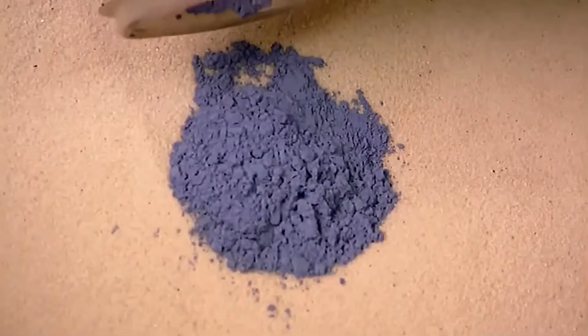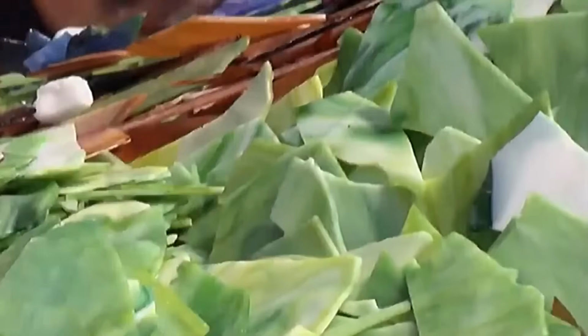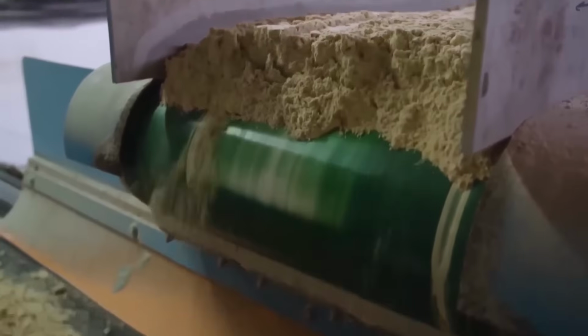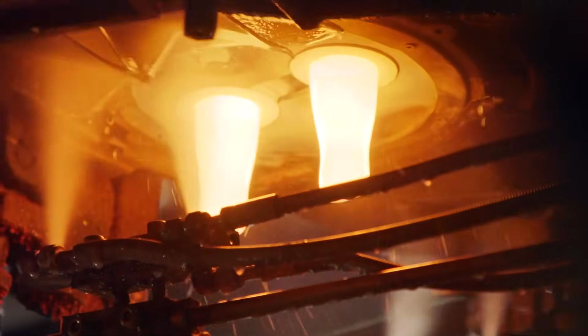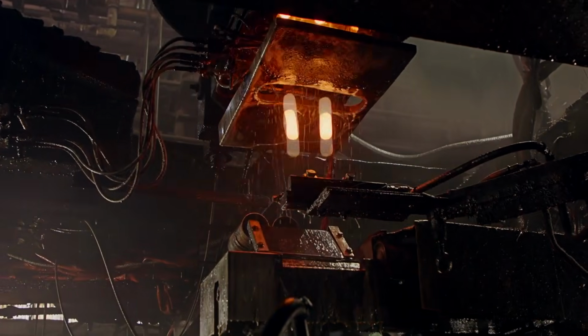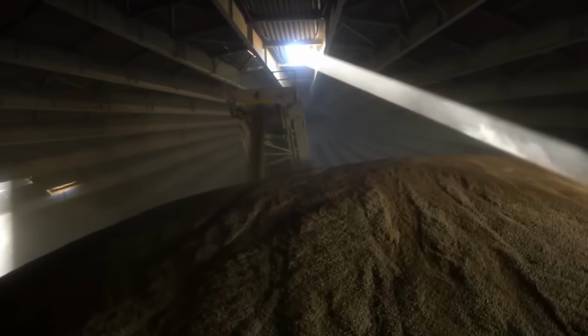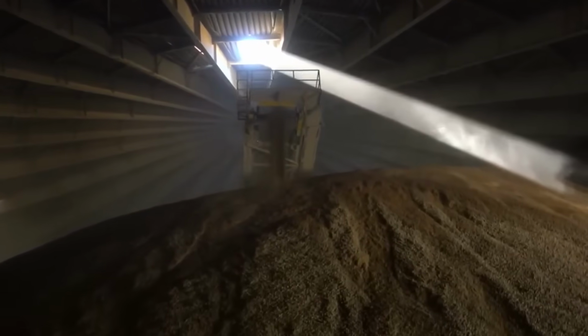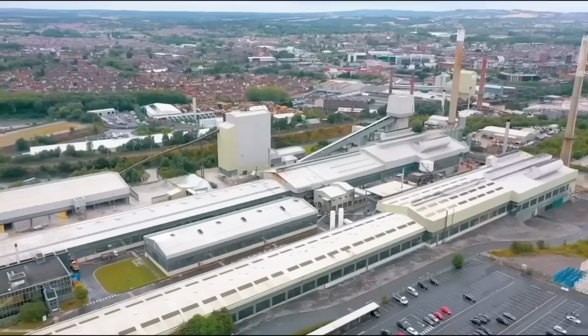The wash cycle runs for several hours per batch, and the overflow water carries the unwanted fines away through a series of settling ponds. After washing, the sand moves into industrial rotary dryers. These are large cylindrical drums, typically 15 to 25 meters long, rotating continuously, while hot air at around 300 degrees Celsius, 572 degrees Fahrenheit, flows through the interior. The drying cycle reduces moisture content to below 0.5% by weight, a specification that matters because residual moisture entering a 1,650-degree furnace converts instantly to steam, creating pressure pockets that produce bubbles in the final glass.